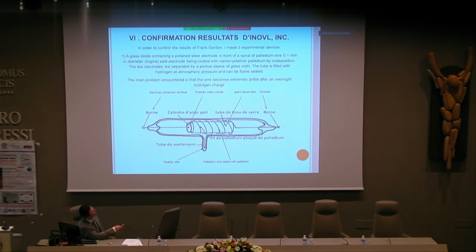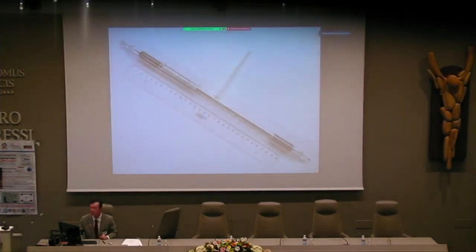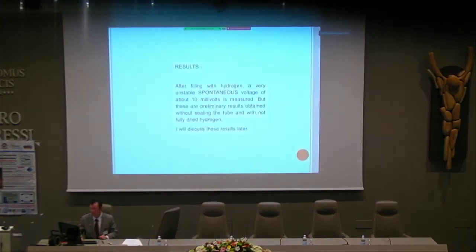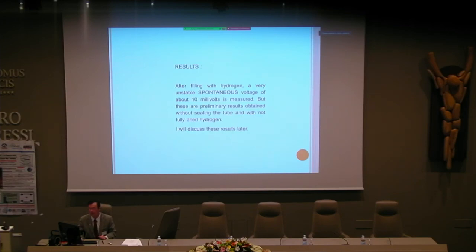It is possible to vacuum the hole, put hydrogen inside and seal the device. It is totally in glass. And I see a spontaneous voltage of about 10 millivolt.